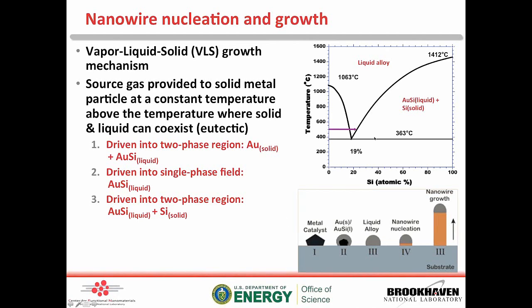And at some point, when you move over into this separate phase region over here, you are supersaturated, which causes the nanowires to both nucleate and grow off the substrate. If your substrate has an appropriate orientation, usually people will use a 1-1-1 orientation, this thing will grow as a nice single crystal, well aligned along the 1-1-1 growth orientation.